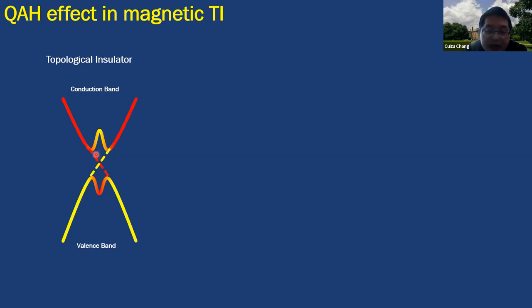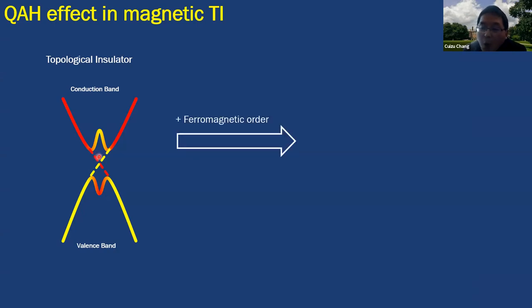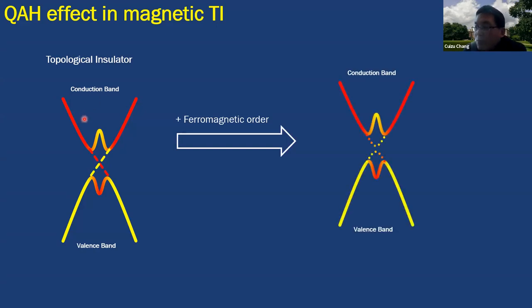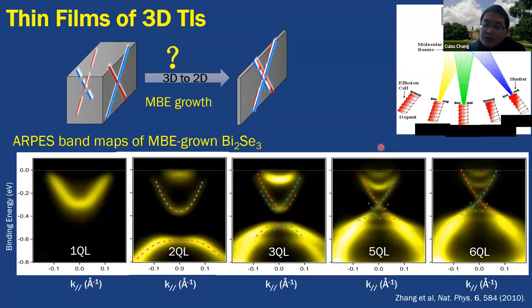This is the topological insulator surface state. It is protected by time reversal symmetry. If we could introduce ferromagnetic order into this topological insulator, the time reversal symmetry will be broken and a gap will open at the Dirac point. So if we could tune the chemical potential into this gap, we could realize the quantum anomalous Hall effect from the theoretical prediction. And this is just the theoretical picture. We are experimentalists. We need to convert this theoretical picture into experimental steps. So next, I will show you how to reach the quantum anomalous Hall from TI step by step.